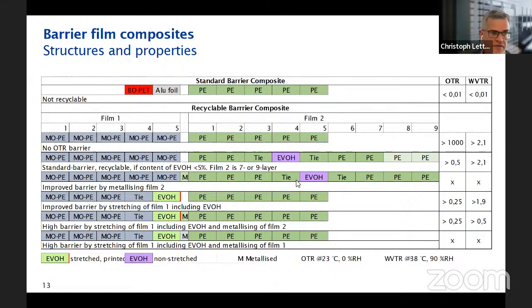We take the EVOH out of the sealant film and put the EVOH into the stretch film, and see that if we do so, we can improve barrier properties compared to the solution where the EVOH is only in the sealant film. If you compare these values, we see in both cases an improvement. The main difference is that now the EVOH was stretched in machine direction, giving better properties. I have to say that the EVOH layer was in this case 4 microns, and here it was 2. So a smaller EVOH layer and even better properties. So a very promising approach here.